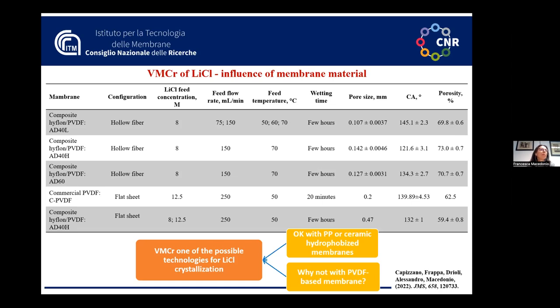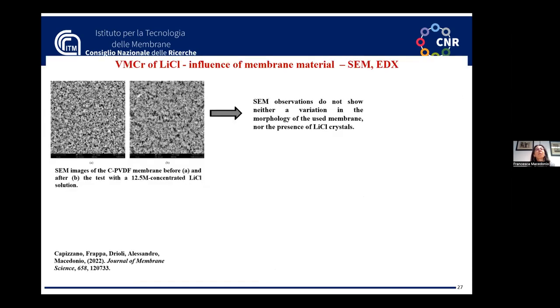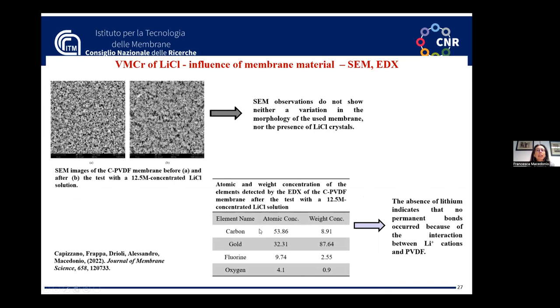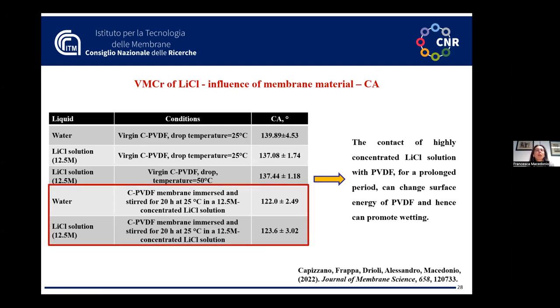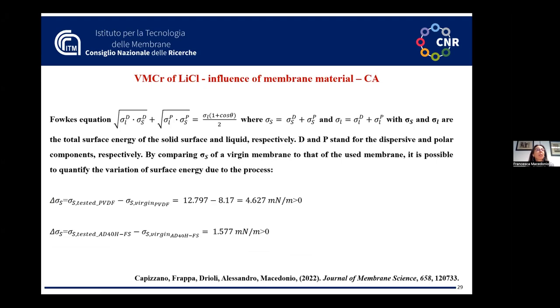Then we tried to understand why the PVDF membrane cannot be used in the case of lithium chloride. First of all, we did some SEM analysis, but we did not observe any difference between the virgin and tested membrane. Also, EDX analysis did not prove the formation of a permanent bond between lithium cations and PVDF membranes. On the contrary, the contact angle measurement proved that the contact between the PVDF membrane and the lithium chloride solution decreased the contact angle of the membrane. Therefore, there is a sort of chemical interaction between the membrane and the highly concentrated solution. This was proved also through the measurement of the surface energy of the membrane through the Fowkes model.